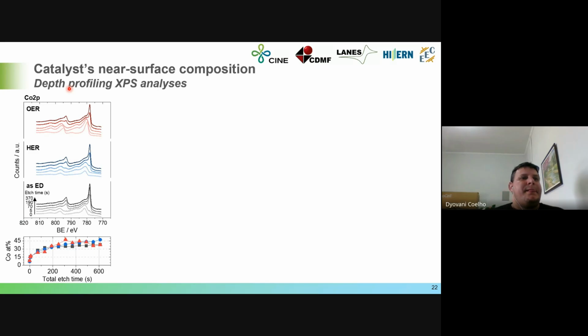cobalt 2p. As you can see here in the cobalt concentration from the surface, here at 0, to underneath the surface, for the near surface, we can see that the behavior is more or less the same for the three situations. This is the as-electrodeposited catalyst, just electrodeposited without use, for hydrogen evolution reaction in blue, and for oxygen evolution reaction in red. The catalyst behavior is more or less similar for both.